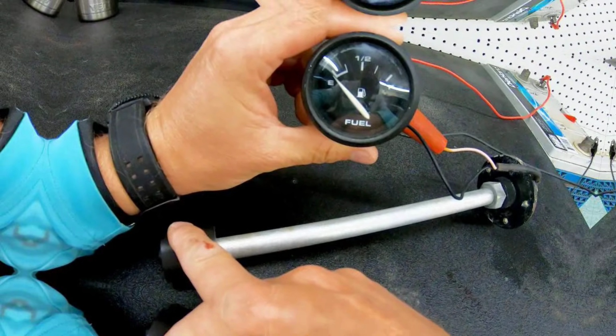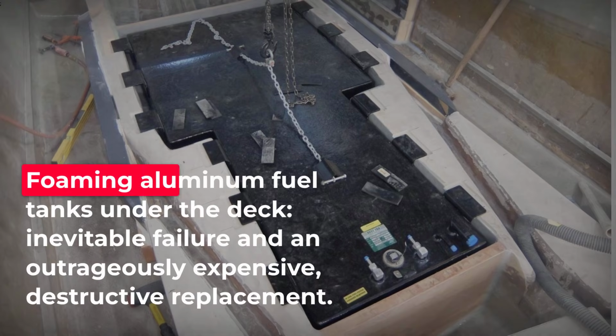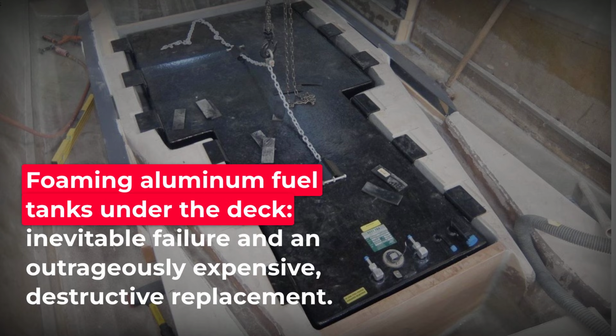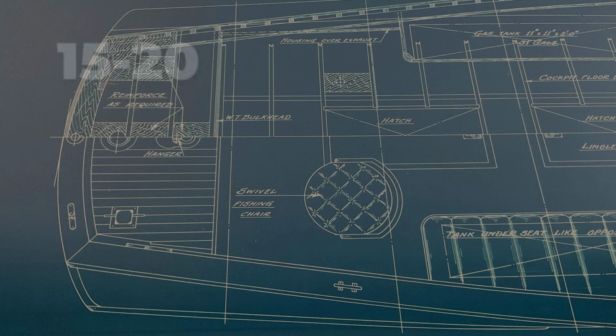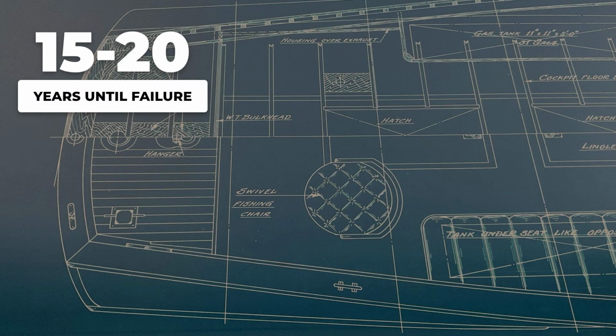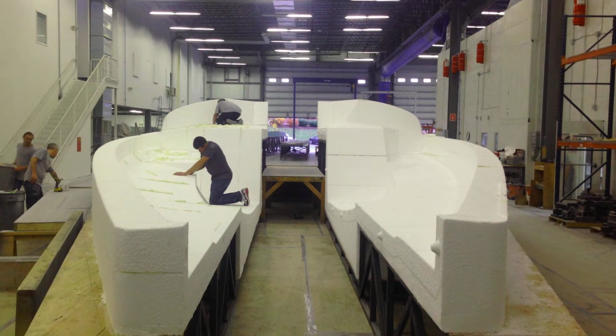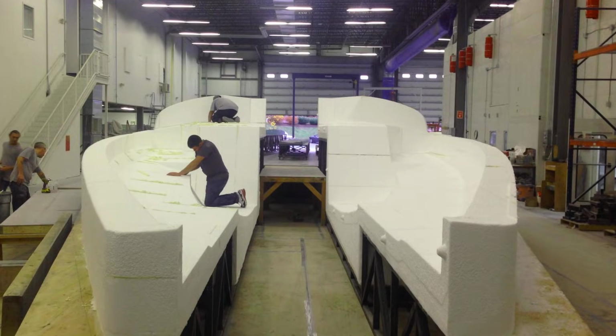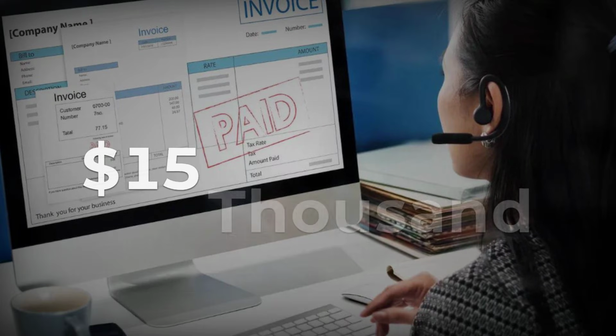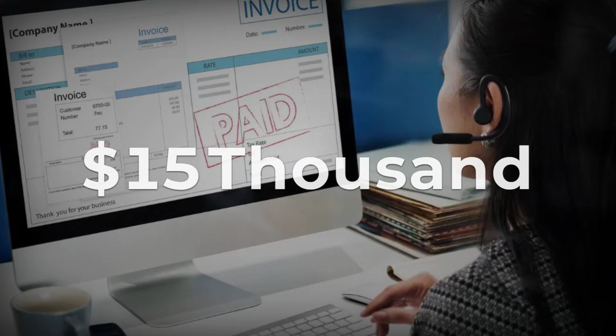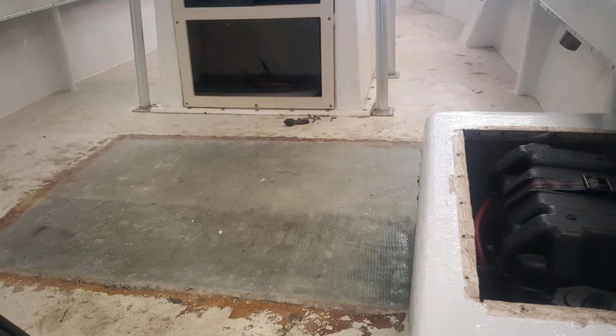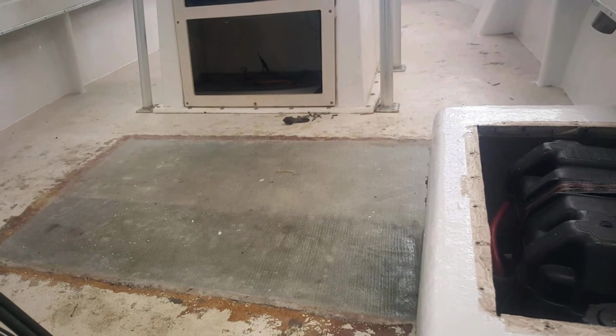and stressing the hull. The worst design in the entire industry is foaming aluminum fuel tanks into place under the deck. When that tank fails in 15 to 20 years, and it will fail, you have to destroy the entire foam structure to get to it. Replacement runs $8,000 to $15,000 on a center console. I've seen it quoted at $30,000 on larger boats.